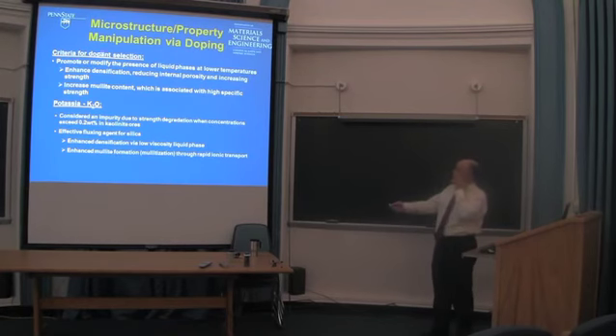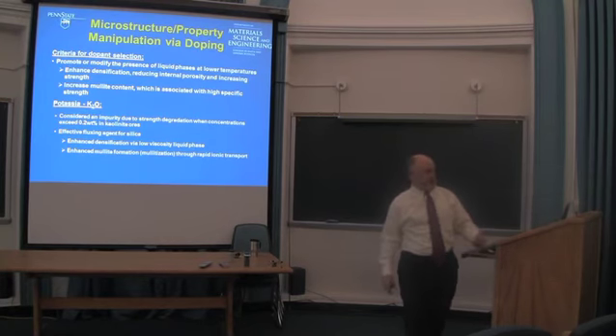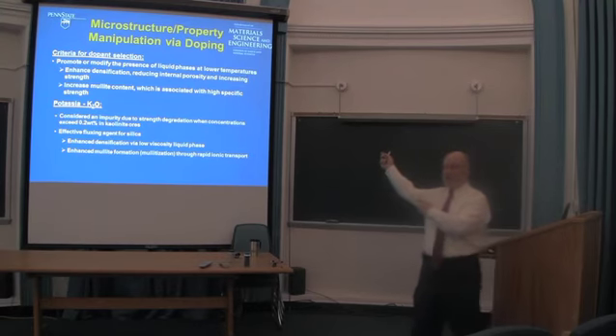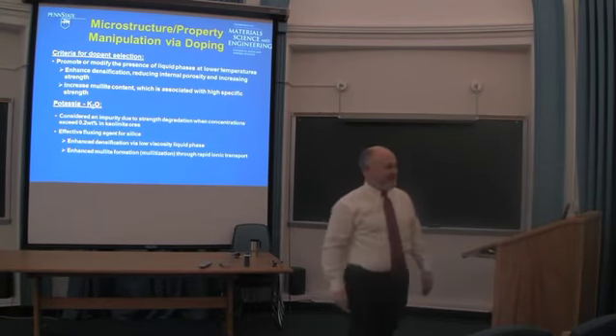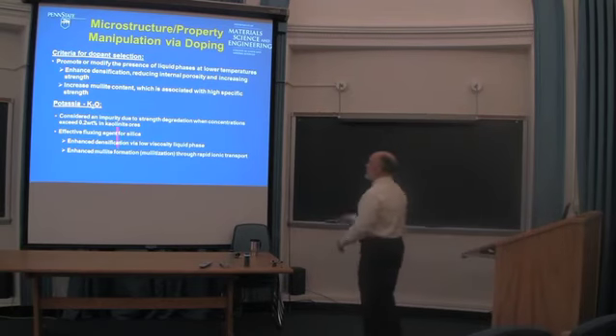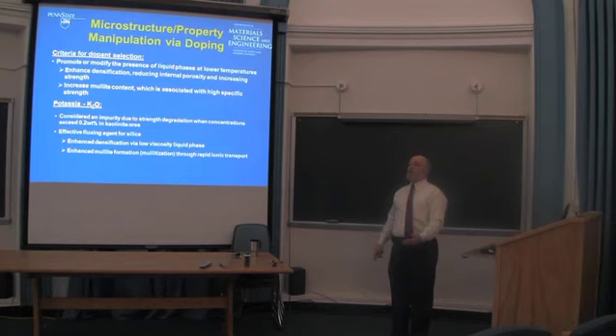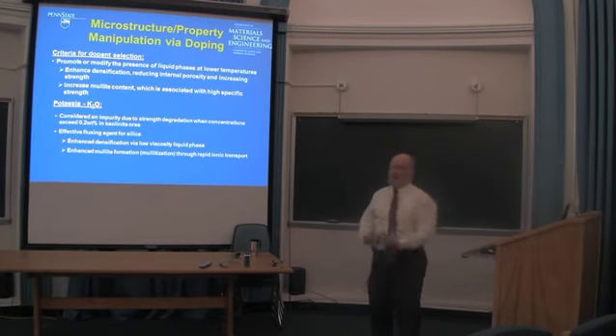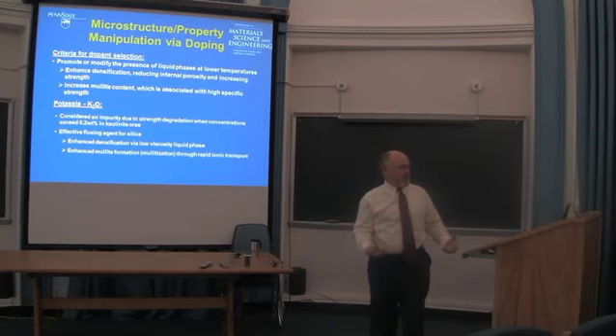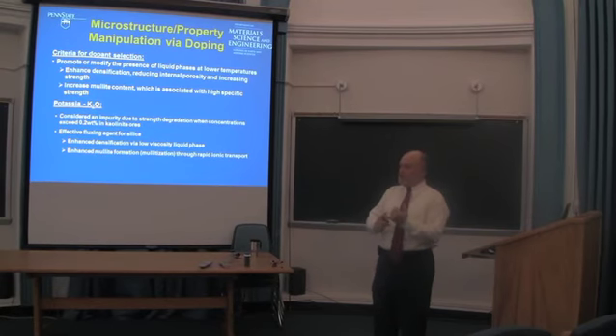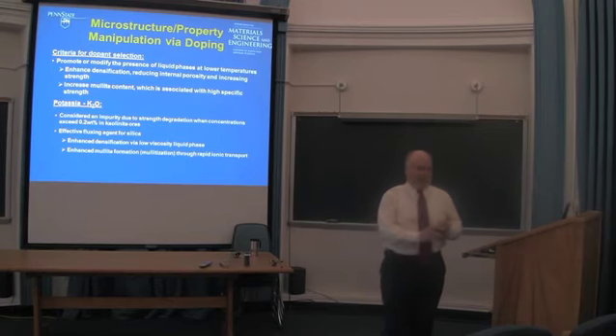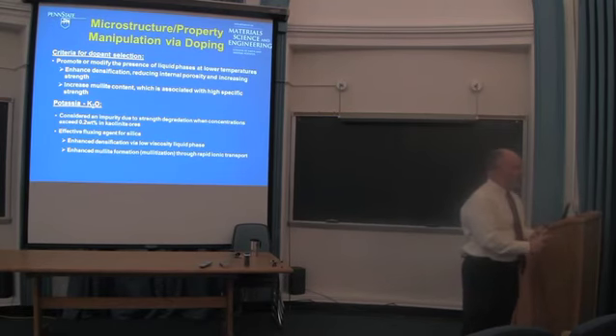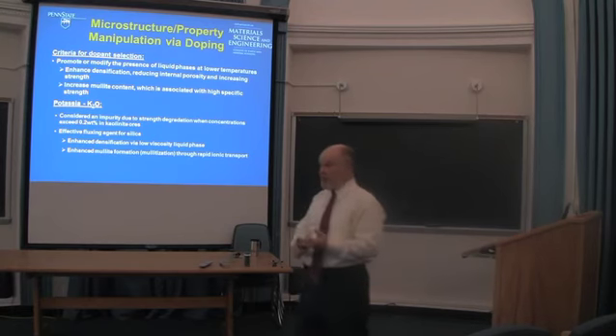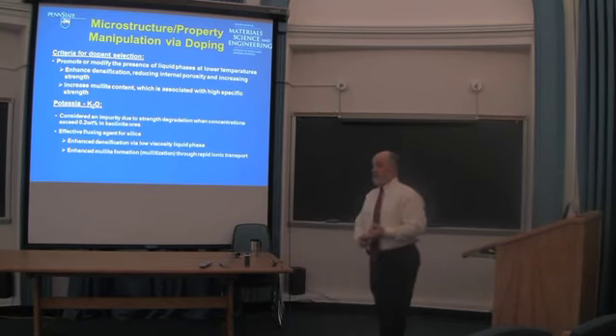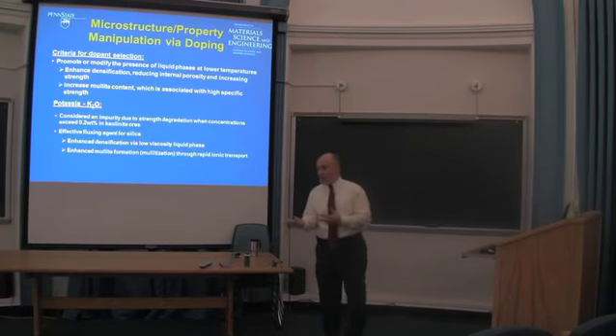All right, so what we did, we said, let's dope this stuff. We want to promote or modify the presence of how much liquid phase we have during sintering. This is geochemistry at its best. All right, it's lava. Okay? We want to increase the mullite content. Mullite is an aluminosilicate, 3 aluminas, 2 silicas, that has a very desirable effect on strength because it gives us acicular crystals in the microstructure, and they're very, very creep resistant, potentially very strong when they're made by a liquid phase sintering process because they're largely defect free. We want that stuff. There's the mechanical aspects of the ceramic world.